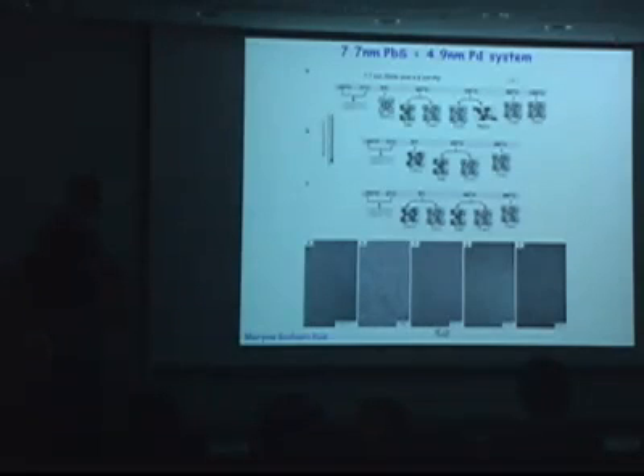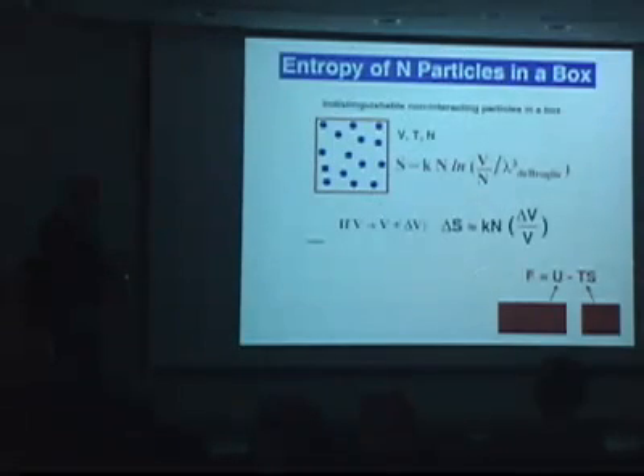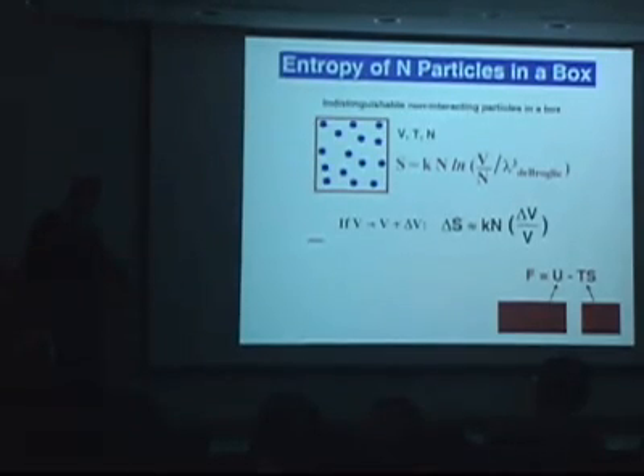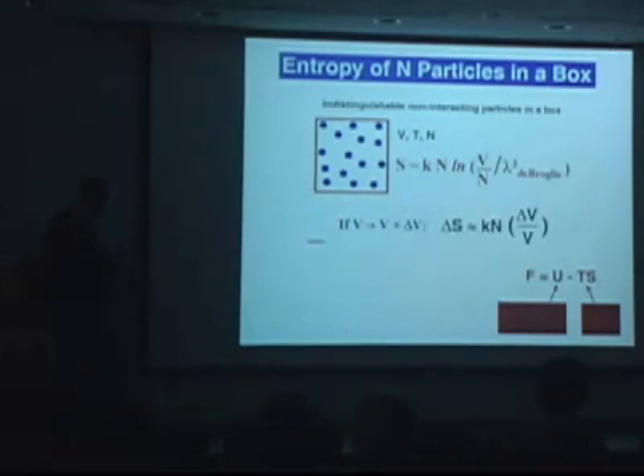From a practical point of view, it's a very nice way to change the phase diagram, to move through the phase diagram. From a more general perspective, it shows that in this equation, entropy has nearly the same weight in the free energy as interparticle internal energy related interaction.